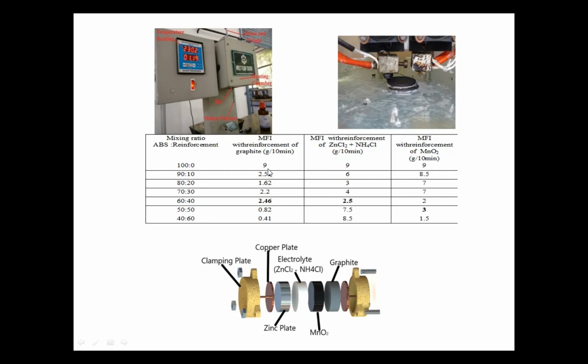So MFI was 9 gram per 10 minutes. Once I put graphite into it in the ratio, let us say 90 to 10, the MFI was 2.51. So you can see there is a reduction in the melt flow index with the reinforcement of graphite. That means if I add graphite into the polymer ABS, you can well imagine how much thinner or thicker a section I have to get, right? So if MFI is decreased, that means I cannot get a thin section, right?